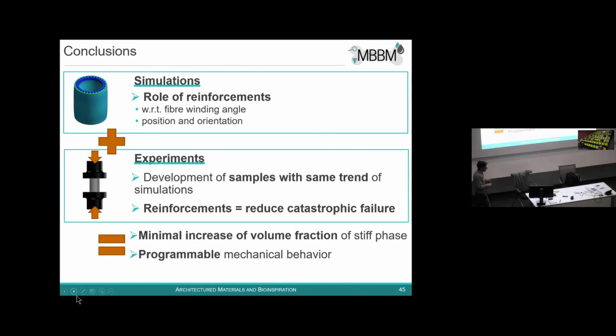To conclude this part, we performed this study to assess the role of these reinforcements inspired by the structure of a wood cell wall. We developed samples which show a similar trend as our simulations. We prove how the reinforcements are avoiding this catastrophic failure. And we find that just a minimal increase in volume fraction, if we place the fibrils in a smart way, allows us to delay failure, and we could obtain a little bit of programmable mechanical behavior.